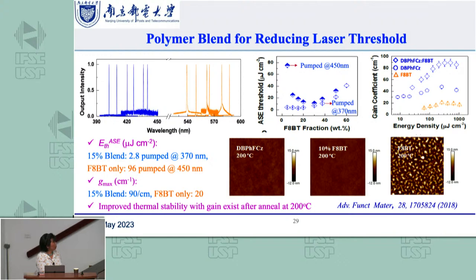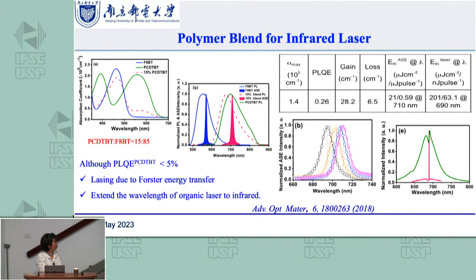And another good thing is we found that because DBPhFCz is very, very stable, you heat it over 250 degrees, nothing changed. But for F8BT, if you heat it over 200, it's totally no gain. But if you blend the F8BT with a small percent, like 10%, 15%, you can see the morphology has no big change. So that is another advantage of this blend system.